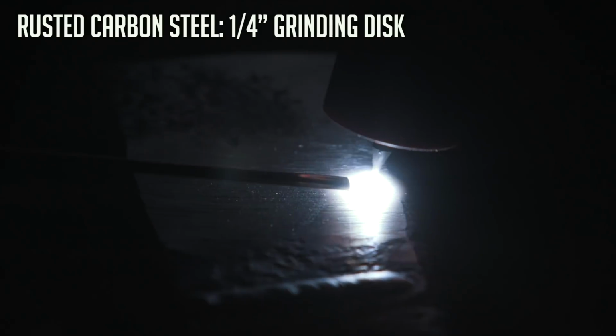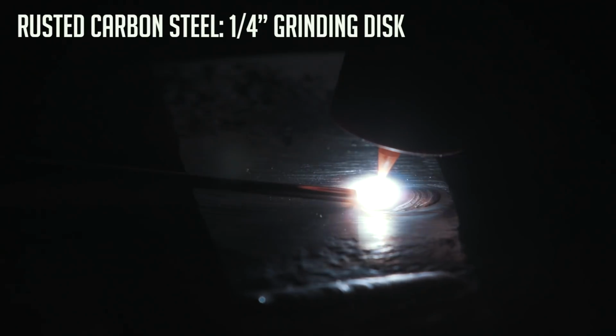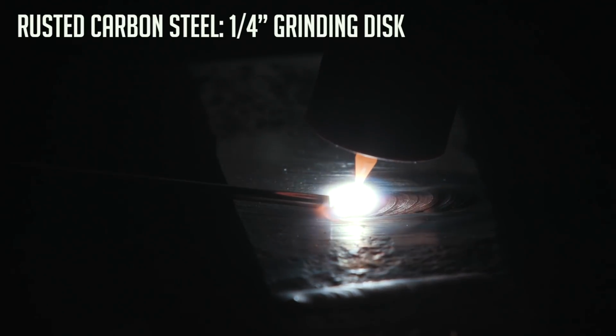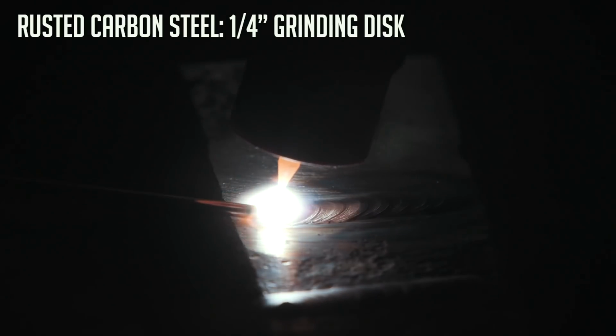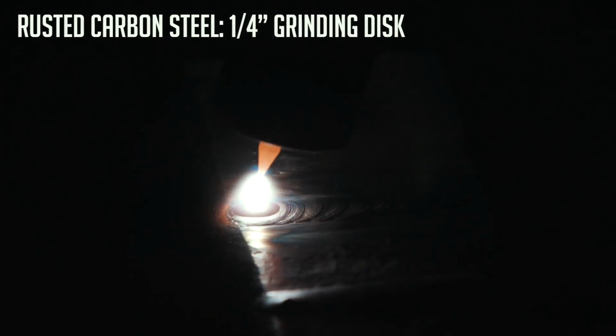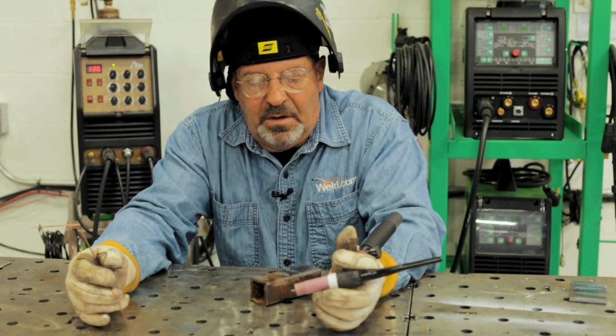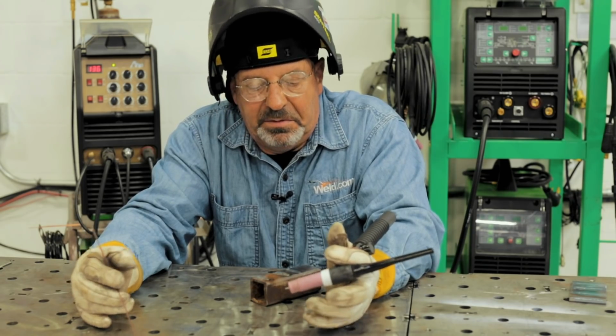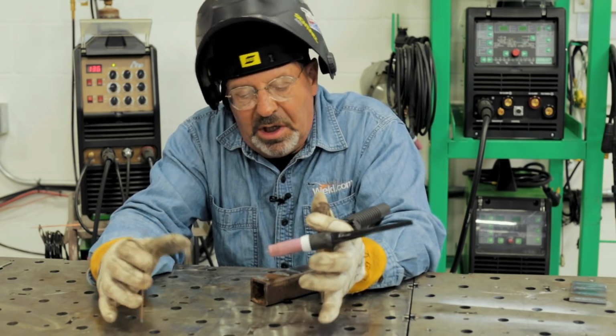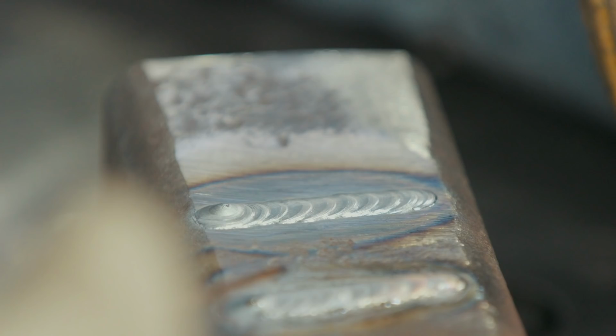The next weld we need to make is on the part here that was done with the 1/4 inch disc. It is cut into clean metal, and that one welded very nicely. It was clean in the weld pool. I didn't have all this surface pond scum floating around, and I could see the weld pool. The edges are a lot cleaner. So I know that material was way cleaner than the rust or where we wire wheeled over the top of it.